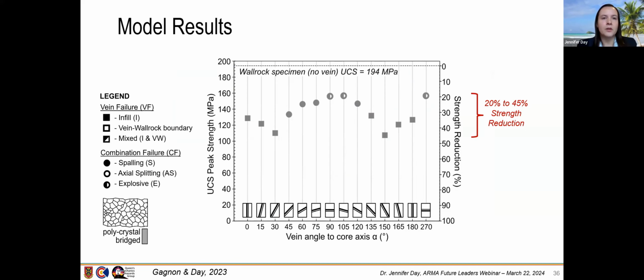angle. And what's important to note in this work is we're not just looking at the vein angle from 0 degrees to 90 degrees, so vertical to horizontal, but because there is anisotropy within the vein itself, we have to model all the way around to capture 0 through 90 and all the way down to 180 to see the different orientation of the vein relative to the core axis itself. So there are some slight differences as you go around, when the vein is inclined one way and then when it's past that horizontal point.